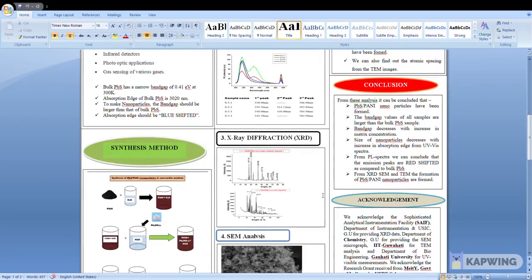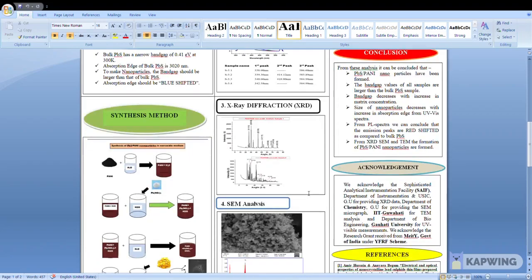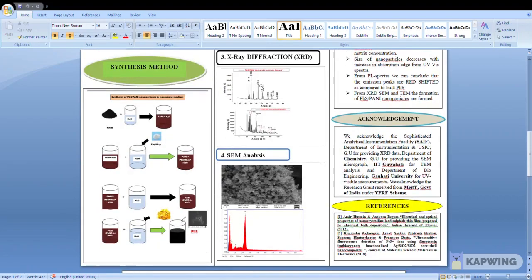From XRD spectra, you can see that we have taken sample 1 and sample 5 for XRD analysis. From the graph, you can see both the samples are crystalline in nature. By comparing with JCPDS data, we found that the Miller indices of both the samples are as shown in the figure. The average crystallite size for sample 1 is in between 28 to 35 nanometer and for sample 5 is 50 nanometer.